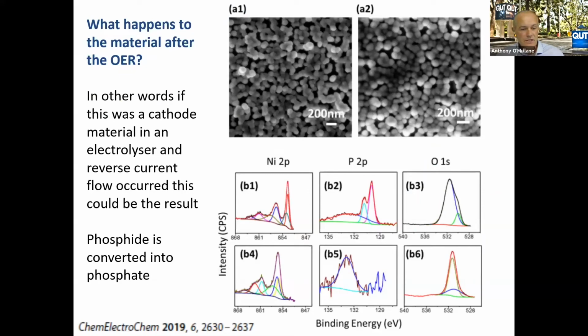So the question is, what's actually happening to that material? We looked at the nickel phosphide in this particular example here on the slide, but if you go to the paper, you can see the analysis on the other materials. Basically what happens in this particular case, after we do a little bit of oxygen evolution, you can see that the phosphide is no longer a phosphide, but it actually becomes a phosphate.